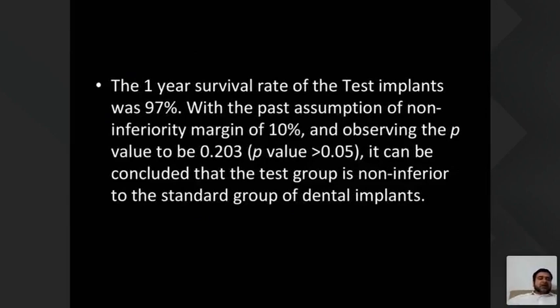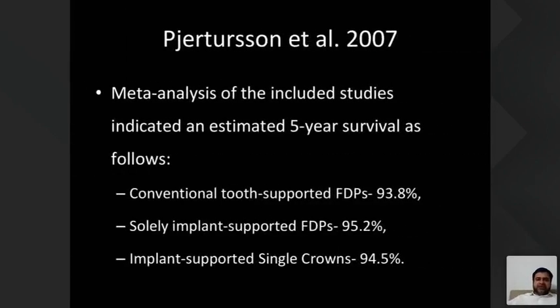So the 1 year survival rate of the test implant was 97% with the past assumption of a non-inferiority margin of 10%. And observing the p-value of 0.203, it can be concluded that the test group is non-inferior to the standard group of dental implants.